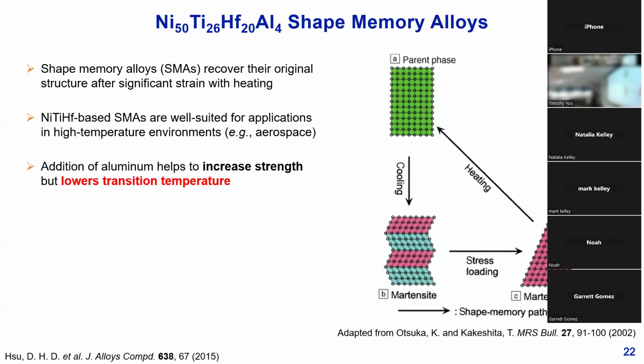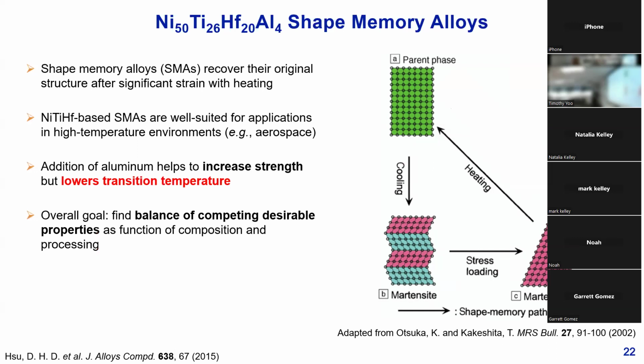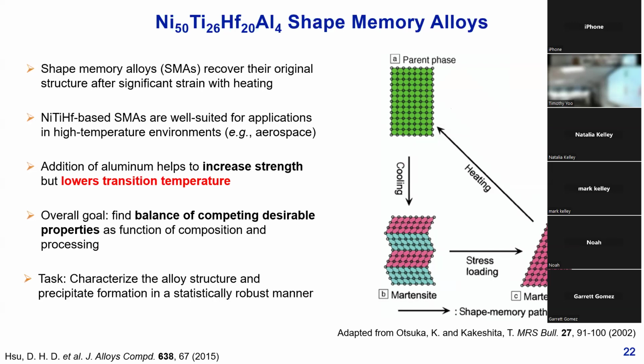And the addition of aluminum recently has been shown to greatly increase the strength of these alloys, but also to lower the transition temperature, which in this case is not favorable for the types of applications that they're being sought after. So our materials design crux now is to find the balance of competing desirable properties as a function of both the alloy composition and the processing methods used to form these alloys. And so our task as microscopists now is that we need to be able to characterize the alloy structure for a given processing parameter and composition combination, as well as the precipitate formation, in a statistically robust manner, again, over larger length scales.